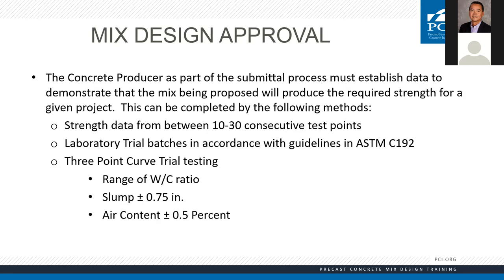How do we use this for mix design approval? How do we prove out a mix? For this process, there are three ways. One is strength data from somewhere between 10 and 30 consecutive test points, and then we figure out the standard deviation. If you have as little as 10 or 15 test points, there's a safety factor involved, which makes it difficult to optimize a mix — it means you'll have to average a lot more than if you had 30 test points.